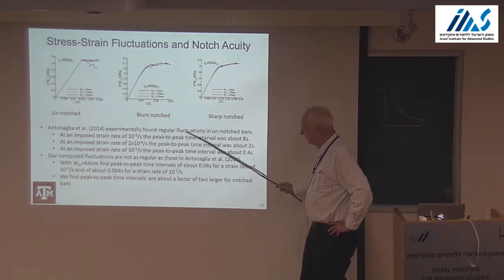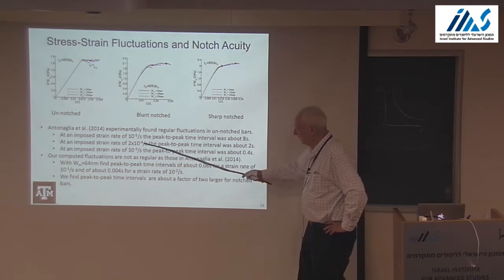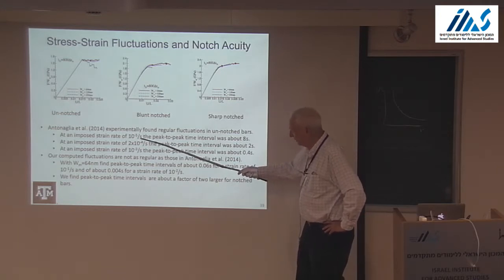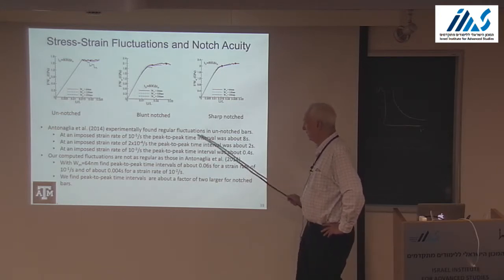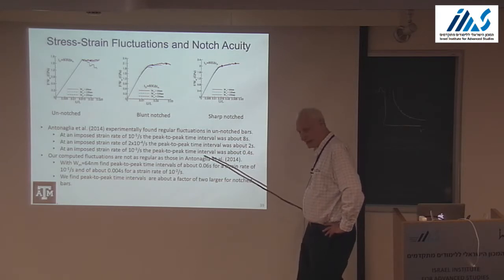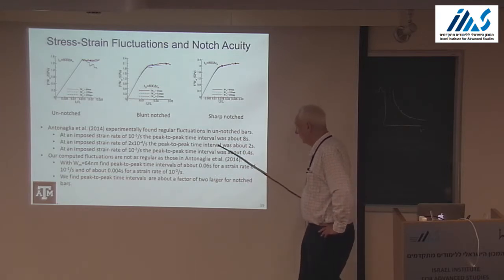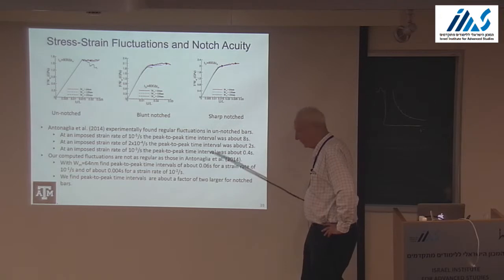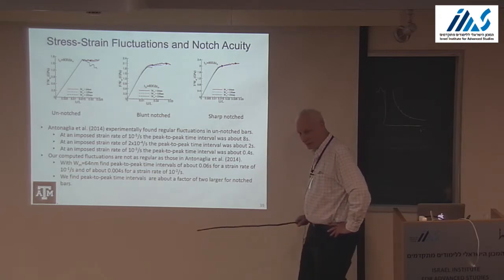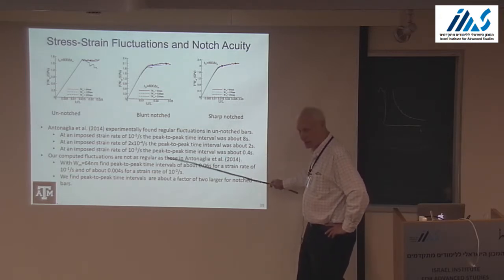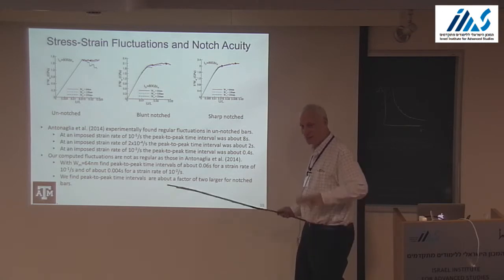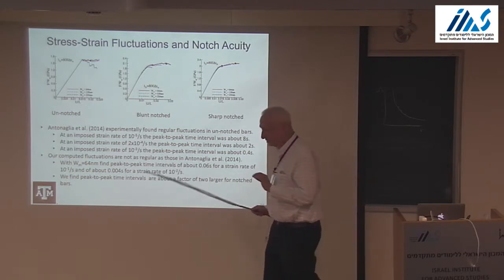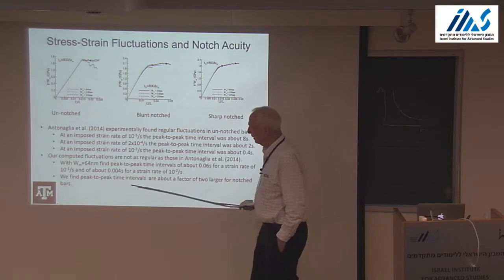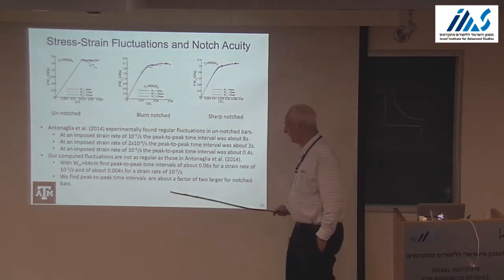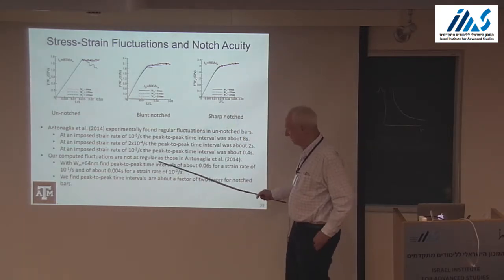They found more or less regular fluctuations at an imposed strain rate of 10 to the minus 5. They found about 8 second peak to peak time. Then it went to 2 seconds, then 0.4 seconds. But you said it's system size dependent. So this is the same size system, different rates. Okay, we see the same trend, but different times.